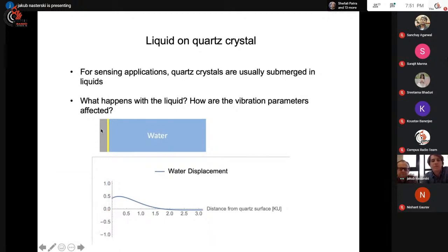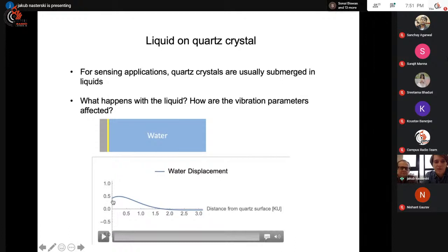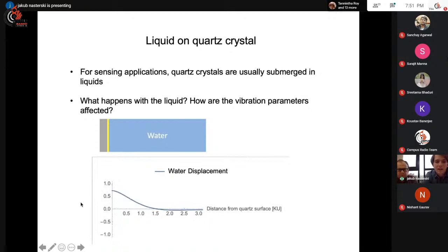I have another animation here. So this is the quartz crystal. The yellow bit is the gold electrode, and say this is water. And then this graph shows you what happens with the water at a distance away from the quartz. So as you see, exactly at the quartz surface, the water sticks to the quartz and oscillates with the same amplitude. But as we go away, the amplitudes diminish until they basically go to zero at some distance. And this is because of the way the water layers shear against each other.